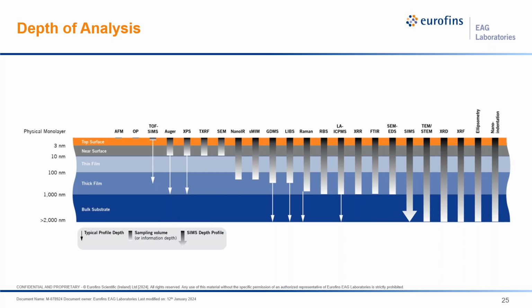And so for AES, XPS, and ToF-SIMS, you can see all of these 3 techniques have sampling depths of under 10 nanometers, so they are optimal for thin film characterization. Alan already talked about sputter depth profiling, and with the 3 arrows you can see on these charts, all 3 of these techniques are also capable of being paired with sputter depth profiling, and we can look at thin films in depth. So if we have structured films, metal layers, adhesion layers, residuals, we can take care of those as well.